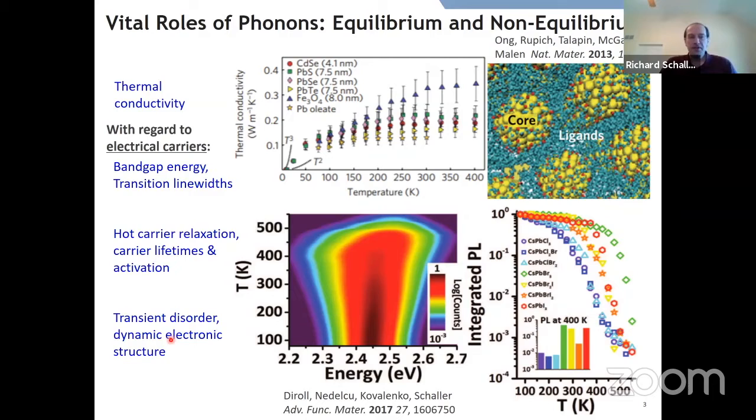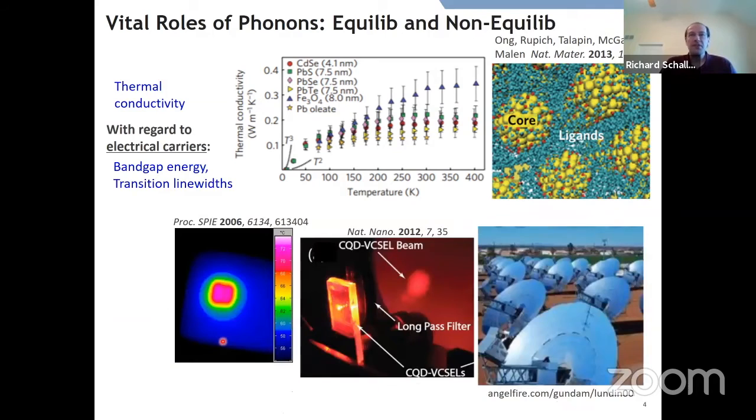And then there are more complex ideas, like what you'd call transient disorder. While phonons are present, your lattice may look different in a non-equilibrium sense relative to what it does at the temperature you suspect the system is at based on static temperature. So you can have the material launch a disordered mode of the lattice for a short period of time, and that itself may change things like transition strengths and lifetimes. These can be important in the actual observed behavior, especially in applications where you might have some form of time resolution, something like a pulsed excitation, for instance.